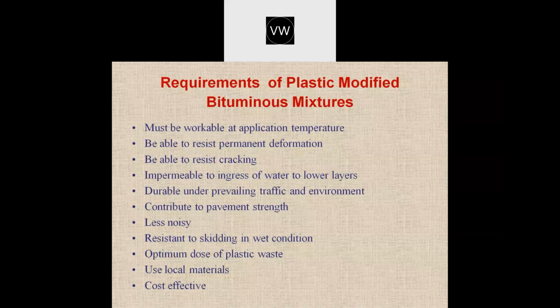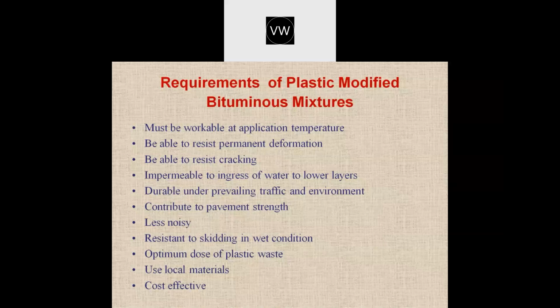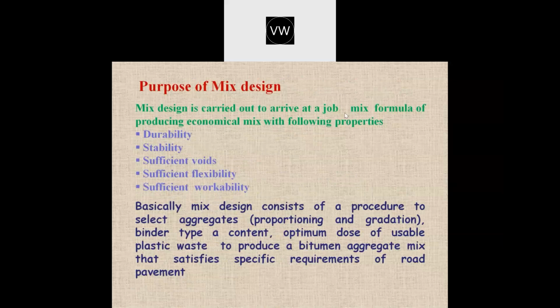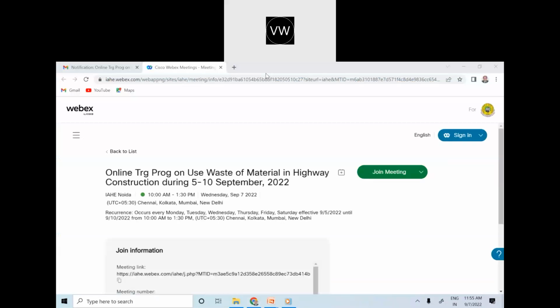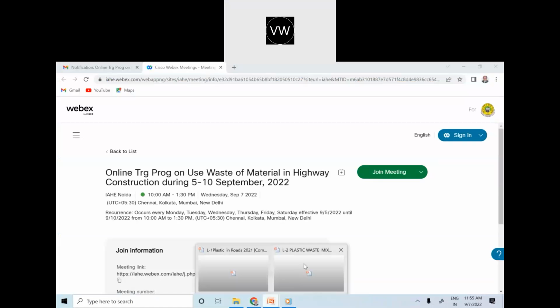So what is a plastic modified mix? It is a mixture of coarse aggregate, fine aggregate, mineral filler, plastic waste, and bitumen. So to design a mix with plastic waste, what has to be done? The well-graded aggregate and the mineral filler, resulting in maximum density when mixed with optimum quantity of waste plastic of appropriate, required specification, and bitumen, result in a mix with good stability, high ITS, and high durability.